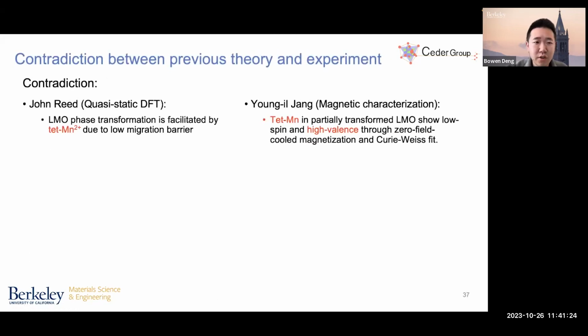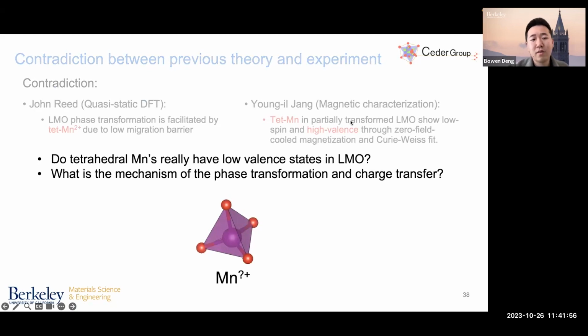So obviously there's a contradiction here, where John Reed argued that this lithium manganese oxide phase transformation is facilitated by this tetrahedral manganese 2+ formation due to its low migration barrier. Chiang's group found in their characterization experiment that the tetrahedral manganese ions in the partially transformed lithium manganese oxide cell show low spin and high valence states. So the question for us to answer is, do these tetrahedral manganese ions really have low valence states in this lithium manganese oxide cell? And what is actually the mechanism of this phase transformation and charge transfer that makes the degradation of lithium manganese oxide cathode material happen so fast at room temperature?